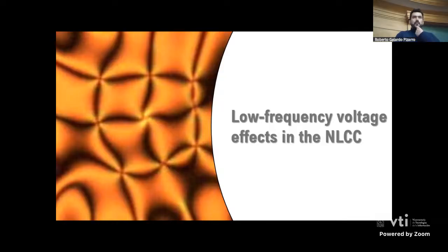And the idea of using a white light source instead of monochromatic light is because the material interacts with the frequencies in different ways, because of the birefringence nature of the material. So, for example, this liquid crystalline material in particular blocks almost all the blue light. So if we use a blue light, it will probably be dark, or we will not have the optimal light to observe the experimental features that we are observing.